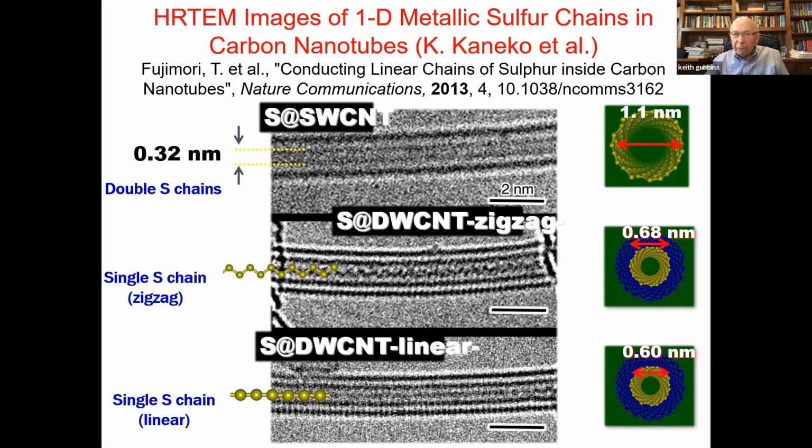So big enough to absorb these 2 layers. And if you look more closely with other experiments at these layers, you find that they're basically a sulfur polymer chain, which is linear. Now, sulfur won't form a polymer chain like this in the bulk because it's unstable, but it's stabilized by the walls of this nanotube. And so there's very strong wall interactions between the sulfur and the nanotubes, and that's what's producing this new phase, nanophase of sulfur.